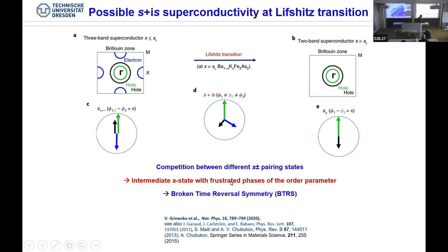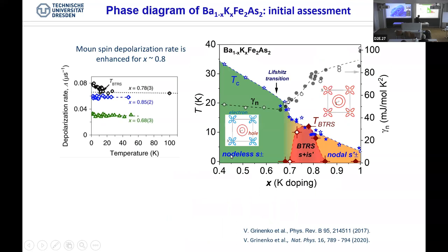Some of these phases were proposed by theory, and this is what we set out to look for. We find it: at high doping around x = 0.65 to 0.87, there is a tiny µSR signal onset — a time reversal symmetry breaking signal — on the right side of the phase diagram. Samples on the left side do not show it. And then the story of what happens just above TC is our next subject. Something can happen: if you really look at the TC dependence on doping, there is a stronger suppression of TC near the transition. Transport measurements from this institute indicate that there are enhanced superconducting fluctuations above TC at higher temperatures in this regime.